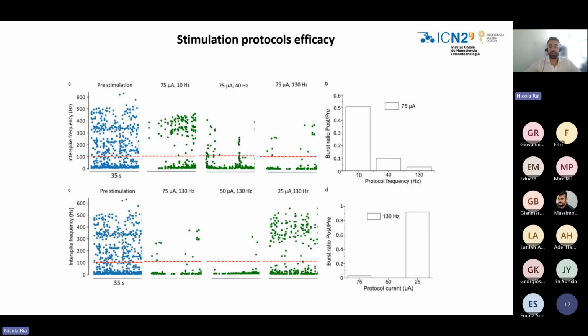Different stimulation protocols were tested to evaluate which is the best configuration to modulate the biomarker. What we observed is that at high frequency, so above 40 Hz, we were able to modulate the burst well, and also starting from 50 microamps. With 25 microamps, we were not able to modulate the biomarker, but starting from 50, yes. This means that it is required to have a charge injection of at least 1 millicoulomb per centimeter square to be able to modulate the biomarker. This is a very high value that, for example, platinum electrodes, the ones available in the clinics at the moment, cannot reach. And this is another reason why there is the need of high-performing material to deliver the treatment with efficacy.